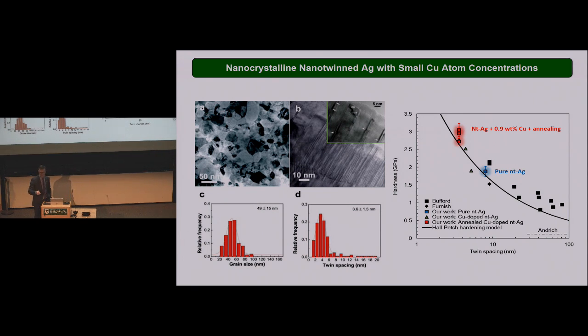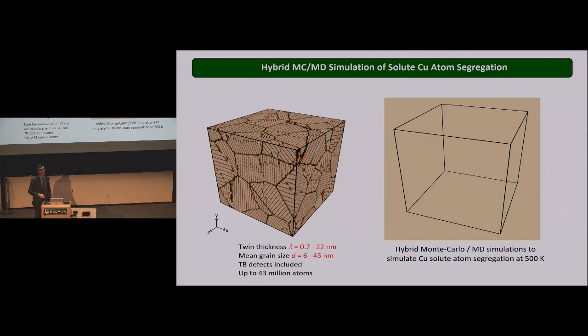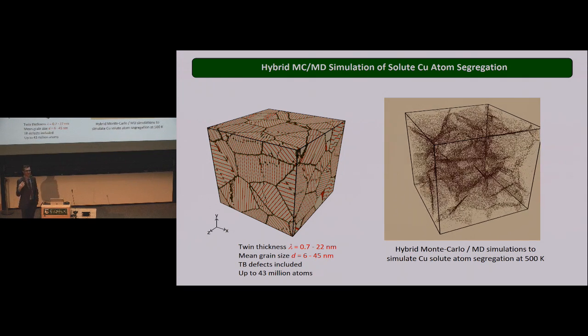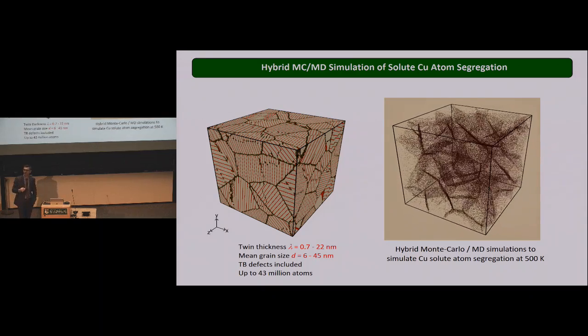And so we use atomistic simulation. In this case, we need to use very large-scale simulation that contains almost 50 million atoms, and that's pretty big. So we need to use supercomputers with 800 CPUs and so on to run this simulation. And so one simulation we did here is we simulate the segregation of copper to the interfaces.